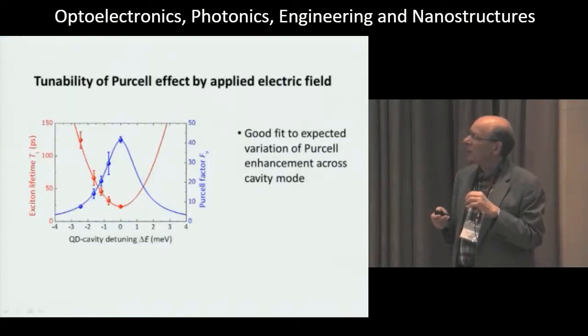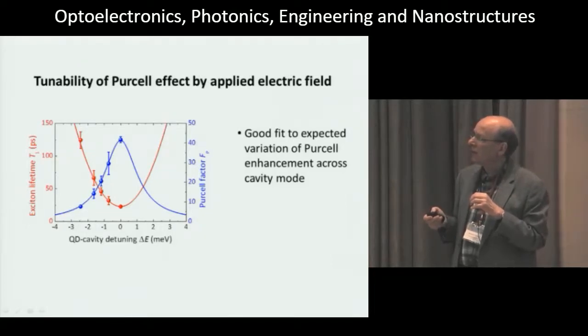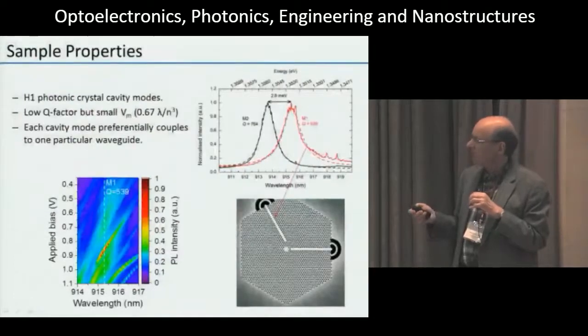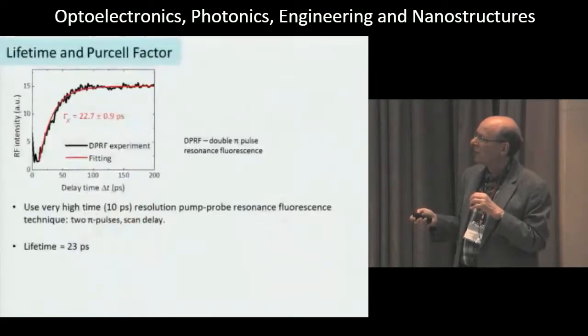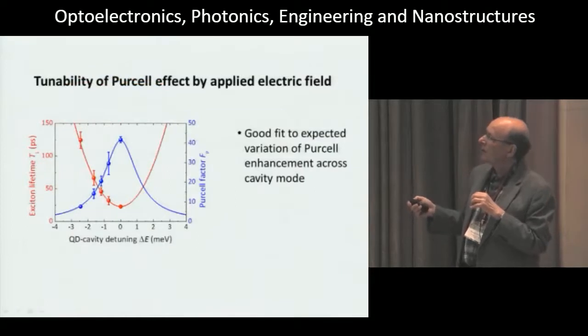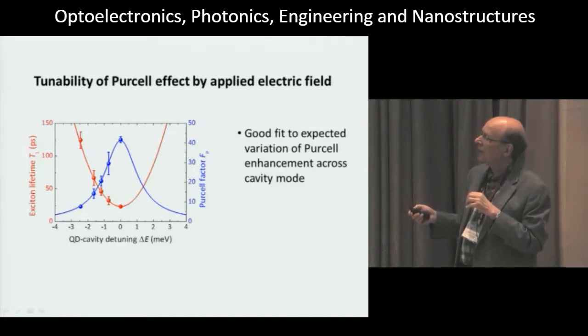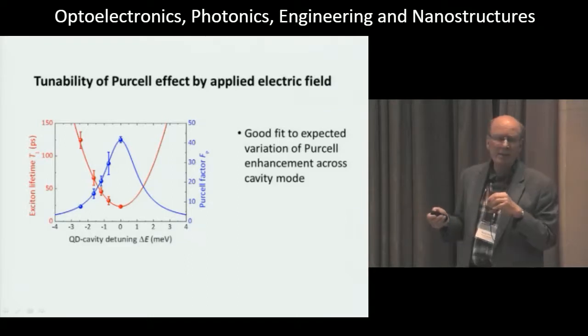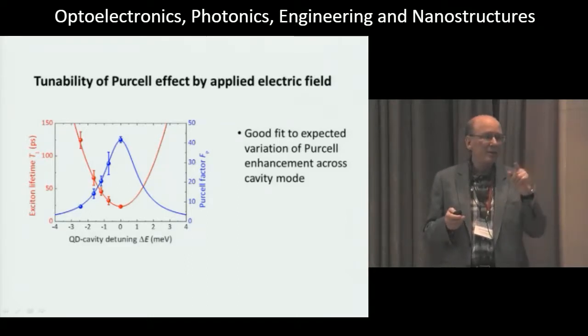And to show that this is indeed a real phenomenon, I've already mentioned we can tune the quantum dot through the cavity. Here is the cavity mode once again. By applying electric field, we can tune the quantum dot through the cavity mode. If it's perfectly on resonance, we have the Purcell factor of 40. Then as we apply electric field and tune the quantum dot away from the peak of the cavity mode, we see that the Purcell factor decreases in a way exactly as you would predict from the width of the cavity mode.